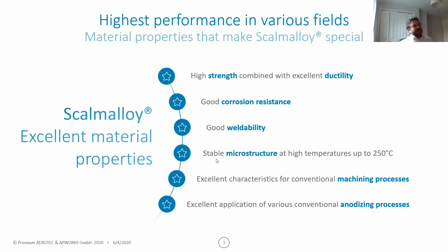You're also having the advantage that to achieve that does not involve a very high temperature heat treatment and quenching cycle, for example, as might be the case with a T6 heat treatment of aluminium silicon 10. So this avoids a lot of issues you might see around distortion, because it's one thing to print the thing the right shape, but if you have to then perform a special heat treatment to achieve a stable microstructure, which involves a quenching step, for a lot of geometries that will introduce a distortion, which if you're going very near net shape can be really challenging to cope with through design.